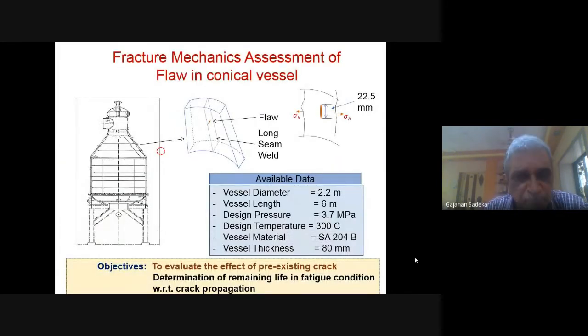This is where this equipment is again in a fertilizer plant. This equipment was supplied, and all radiography, all NDTs were done, everything was done. After operation, after something like 1.5 years, because generally all fertilizer plants, all critical equipment, they carry out the NDT of the major weld seams. They carry out the major NDT in order to see whether any cracks have developed. So on this equipment, they carried out the NDT and they found that at this location, if you see this, there's a crack on the weld seam,